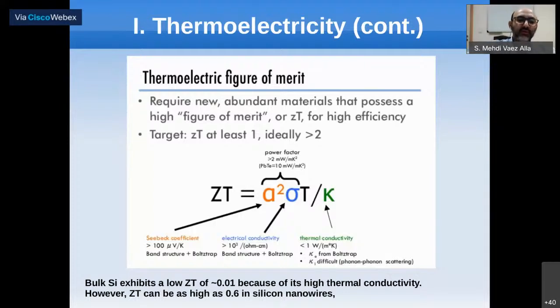For example, bulk silicon exhibits a low ZT value, about 0.01, because it has very high thermal conductivity. And one possible way of using silicon for the thermoelectric effect is to kill thermal conductivity. By decreasing the size of the system, as I will address in a few slides, it is possible to kill thermal conductivity and increase the figure of merit parameter. But it is not sufficient since the ideal value is higher than 2.